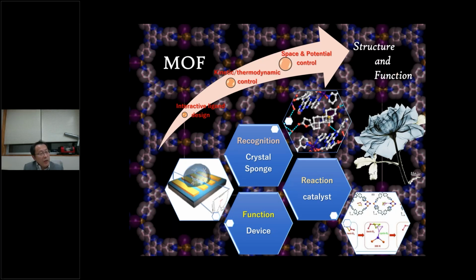Currently, we are working on these projects. One is using the molecular recognition ability of a MOF. We do a crystal sponge. Crystal sponge research means if you can encapsulate your target gas molecule in a pore, you can determine the molecular structure by X-ray analysis. So even if the gas molecule is not crystalline, doesn't crystallize, as long as you can encapsulate the gas molecule, you can determine the molecular structure. This method was developed by Professor Makoto Fujita at the University of Tokyo in 2013. Our MOF really works well as a crystal sponge.